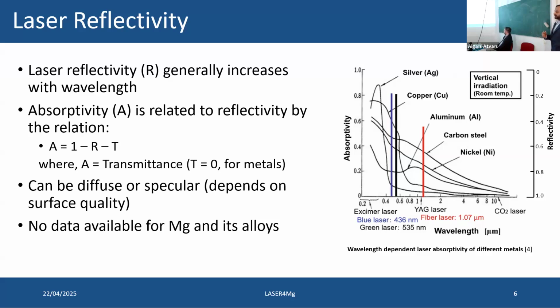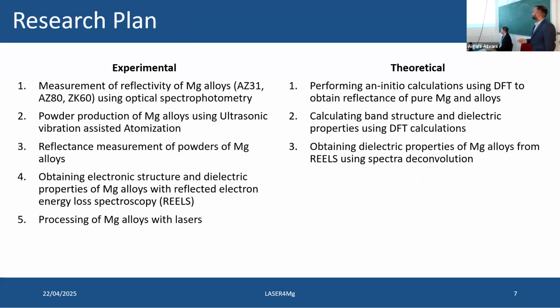One case in point is that similar work was done for copper, and they found that the best laser for processing copper would be a green laser, 535 nanometers, which increases its absorbability by 50%. Here's a brief overview of the experimental and theoretical research plan that was followed. These three are the most common industrially used magnesium alloys: AZ31, AZ80, ZK60. The AZ just means aluminum and zinc, which are the additives into the magnesium, and ZK is zinc and zirconium.